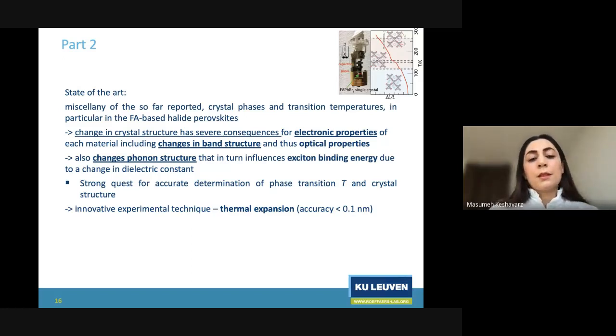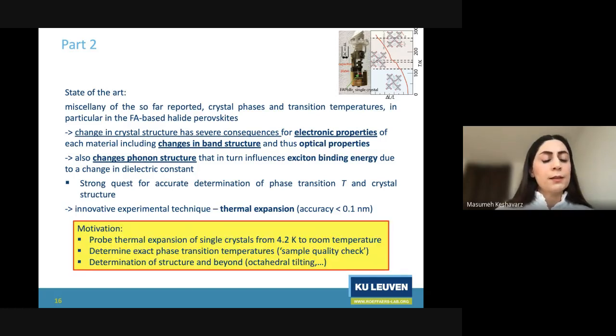So there is a strong quest for identifying the transition temperatures in the crystal structure for different phases accurately. Here our approach was, for the first time, to use thermal expansion measurements, or dilatometry measurements, which have an accuracy below 0.1 nanometer, below angstrom accuracy. The motivation here is to probe the thermal expansion of single crystals from 4.2 K to room temperature, determine the exact phase transition temperatures, perhaps check sample quality, and, using some complementary techniques, identify the phases of the material as well.